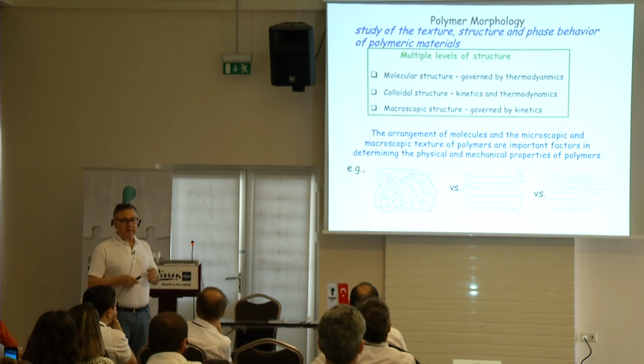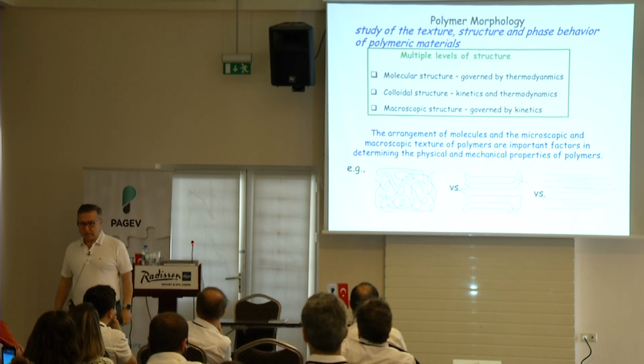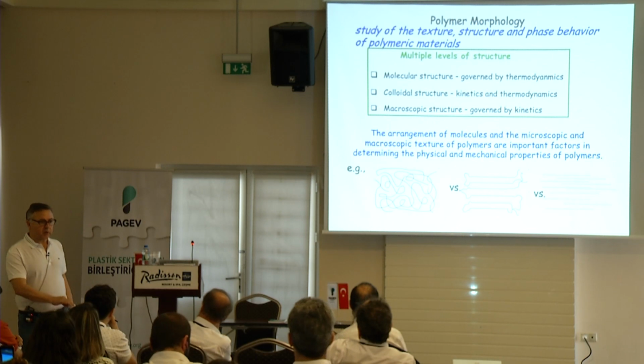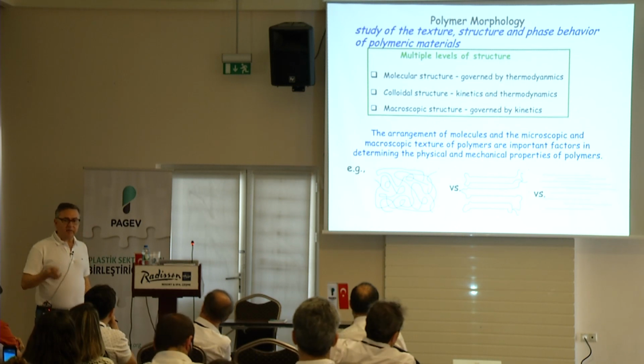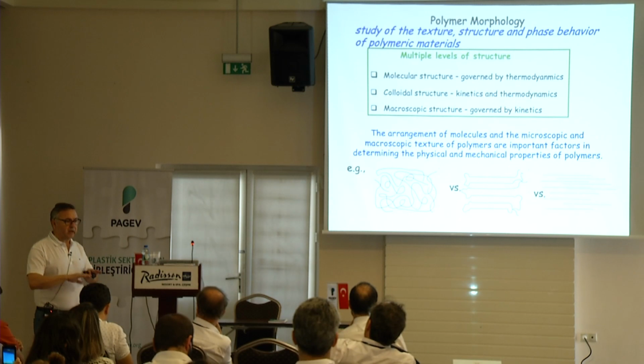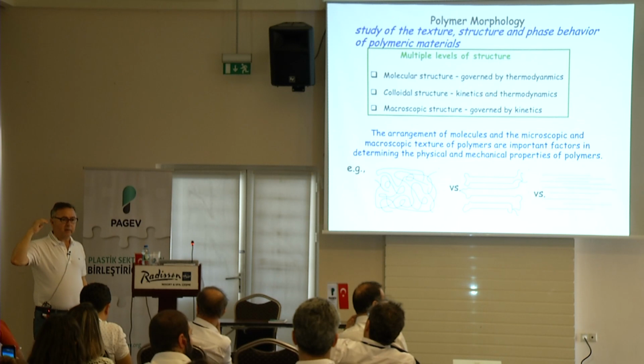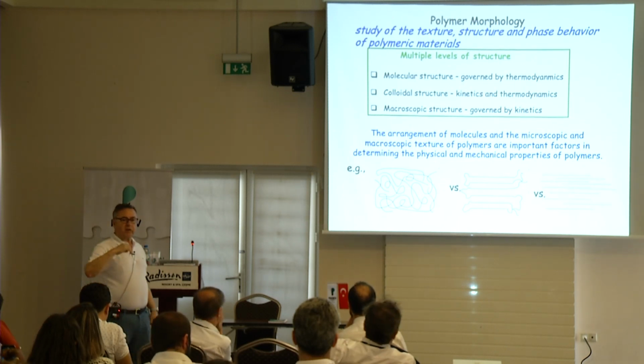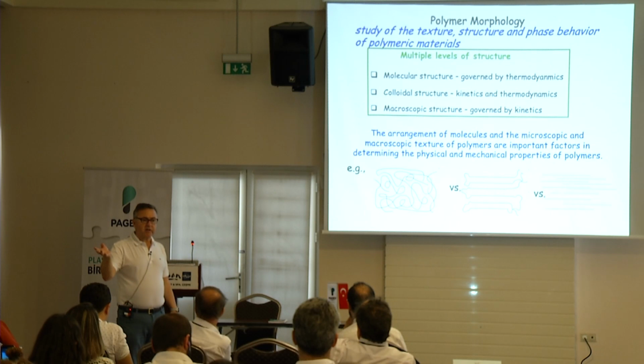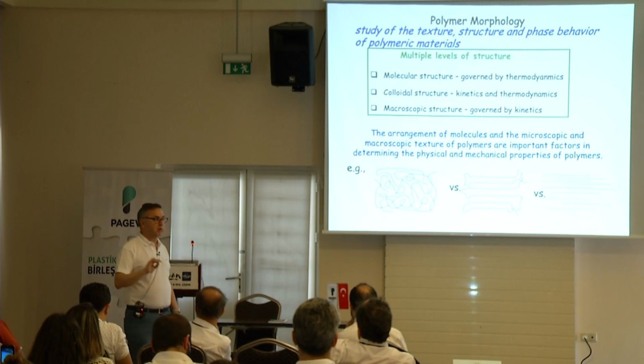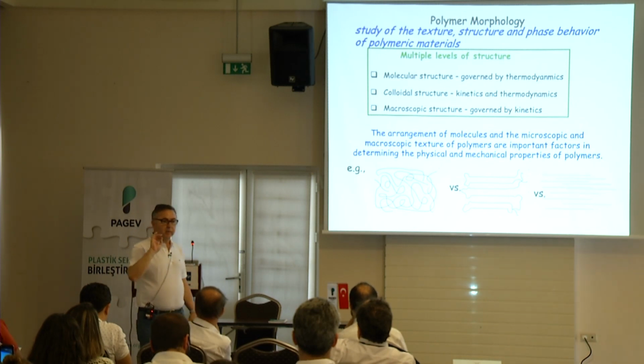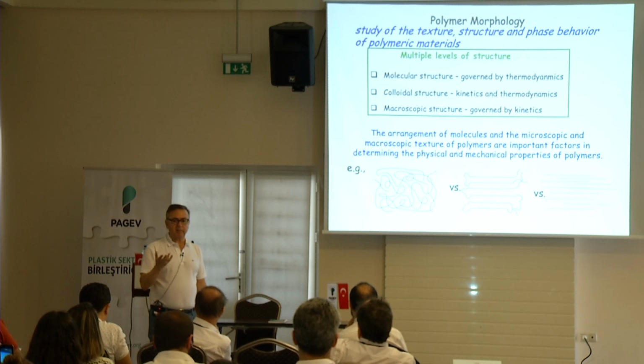And one of the most important things that you must remember in the case of polymers, compared to small molecules, is that polymers are never at equilibrium. This is an important concept: no matter what you do, they will not go to their lowest energy state. They will always stay at some non-equilibrium state. And because of that, you have issues of thermal residual stresses and density changes over time. Aging is an important issue. And this is what we polymer engineers live with.